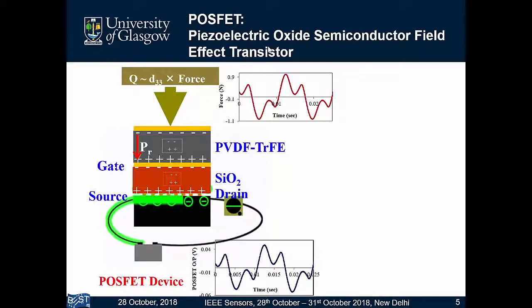In the first run, we tried PVDF-TrFE because it's a flexible piezoelectric material. It can conform to any substrate, and it's easily processable. That's why we used PVDF-TrFE. But the problem with PVDF-TrFE was that it's a very good piezoelectric material, but it's pyroelectric as well. So it responds to both pressure and temperature.